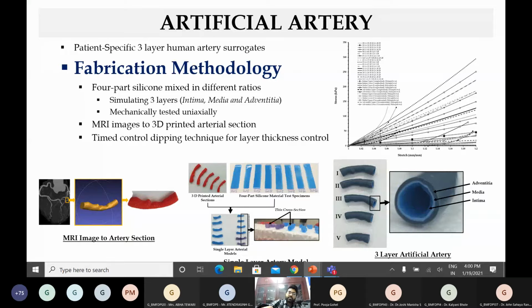If we dip something in a very non-viscous liquid, it's going to fall apart, right? So how do we dip this to make sure there is a certain layer thickness, which is exactly the layer thickness of the intima, media or adventitial layer? And please mind, this is a very small layer thickness. We are talking about certain microns. So how do we mimic this micron based layer thickness? So through research, what we did is we looked at